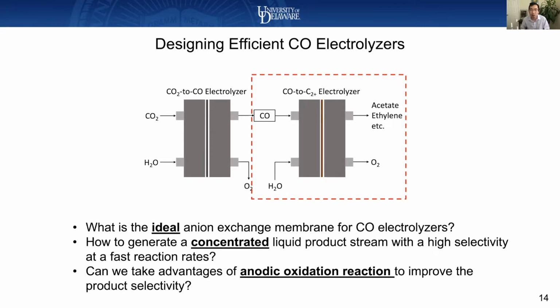Okay, so this concentration is actually very important for your product stream. If you think about an engineering environment, you want to have a practical system. If you have a very diluted product stream, it's really difficult to separate out, and the energy cost for separation is extremely high. So what you really want is a highly concentrated product stream. But how can we engineer the reactor in a way to promote the concentration? And the last point I mentioned is that we observed the anode reaction can help us to address some of the product selectivity issue.